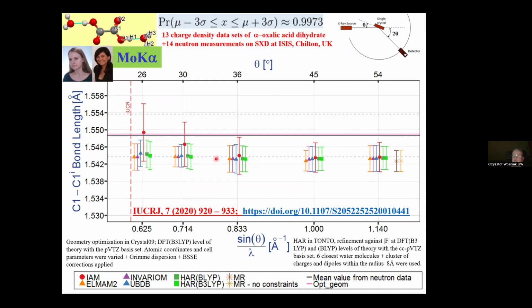These triangles, squares, and circles are showing the average values, whereas these intervals are confidence intervals calculated at this level, meaning the average plus minus three sample standard deviations. And we use this data in such a way that we are refining against them the independent atom model, approaches utilizing pseudo-atom data banks, and Hirshfeld atom refinement at two different levels of theory. And what we see is that this bond is dependent on resolution, but above a certain resolution, which is